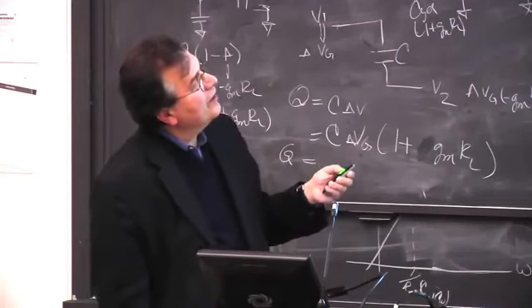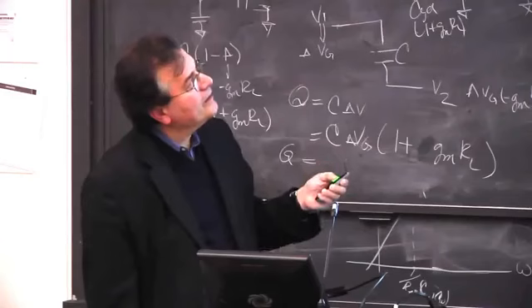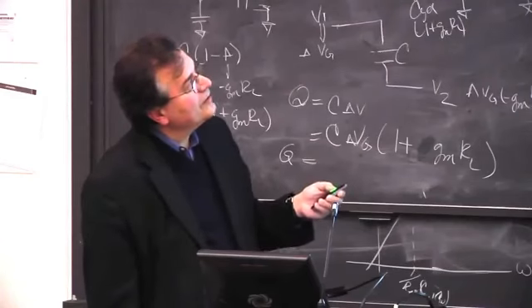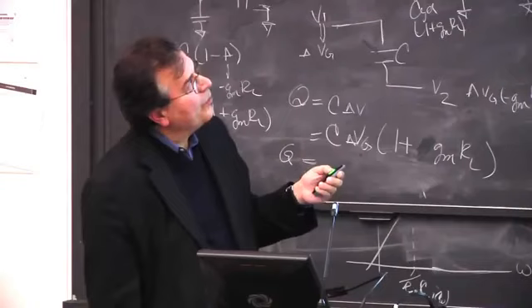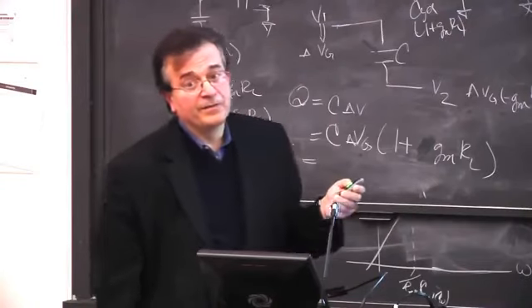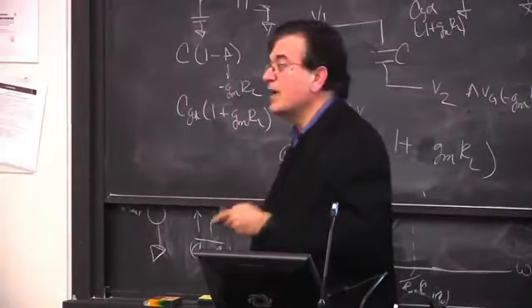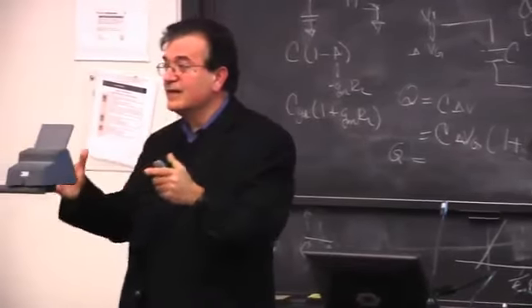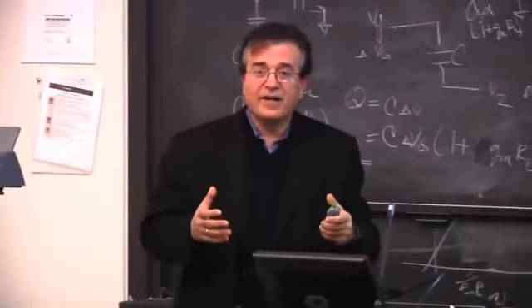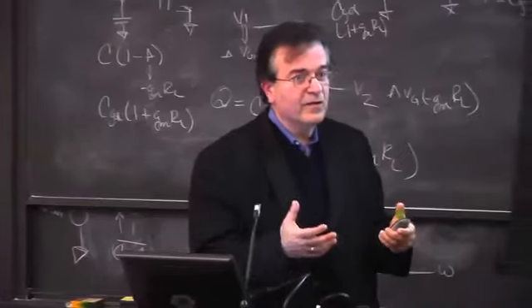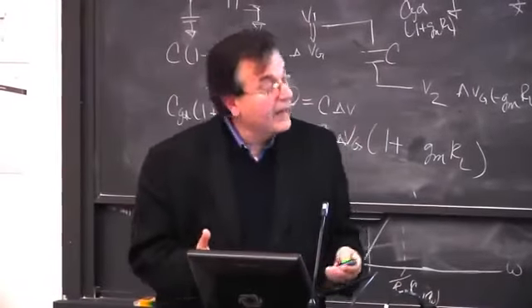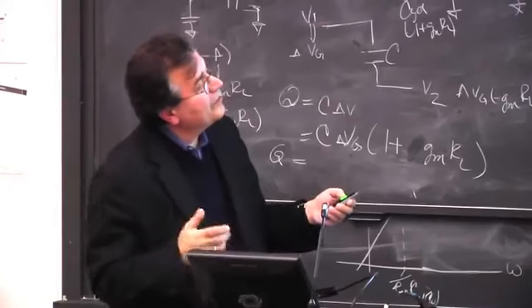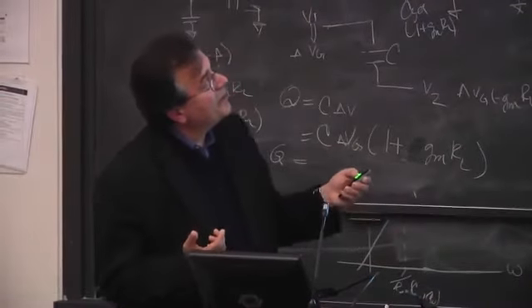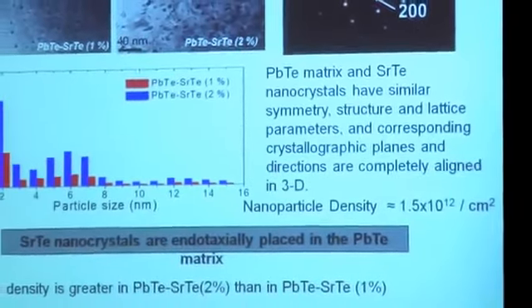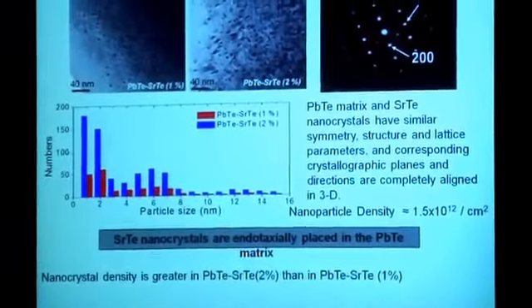You might say, of course I get more because I have 2%, but it's not necessarily true. You can get the same number, only bigger. If it's the same number, only bigger, you get less interface area. It's the interface that scatters the phonons. So you need to maximize that, and when you do, you get the maximum effect. So if you get bigger particles, and they're equal in number or even fewer, then your thermal conductivity begins to go up again. And that's what we observe.